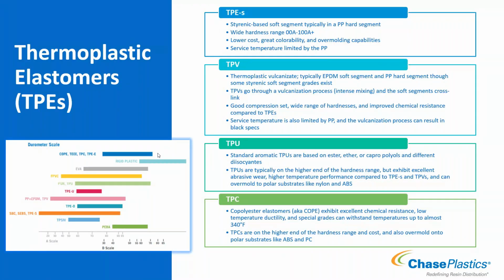Styrenic based TPEs typically have a styrenic based soft segment - an SBS, SIS type soft segment - generally in a propylene hard segment. Really good wide range of hardnesses, from double zero A's all the way up to 100A. Generally then we start getting into the D range - good low cost option. So if I need something to overmold and I just need a nice soft touch feel, TPE is a great option for that. Great colorability, great overmolding capabilities. Because of the propylene hard segment, it wants to inherently overmold to propylene and ethylene, but you can formulate grades that are specially made to overmold onto other materials - ABS, PC, nylon - they can be made to do that as well.